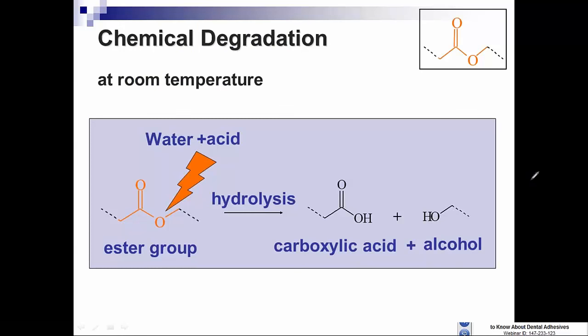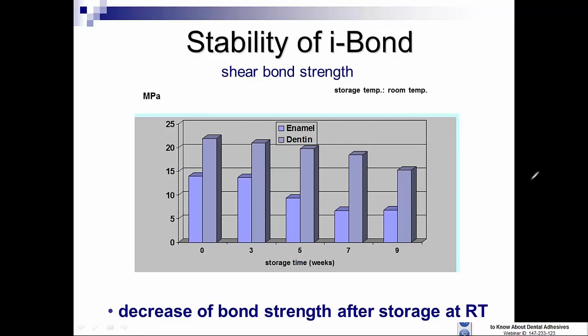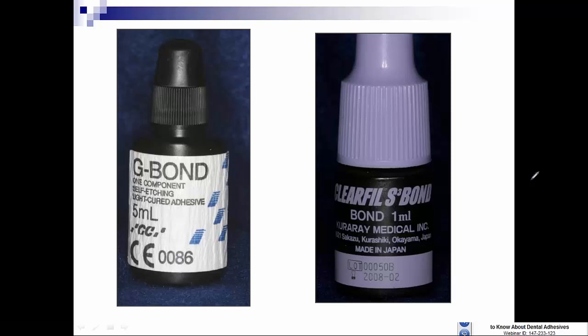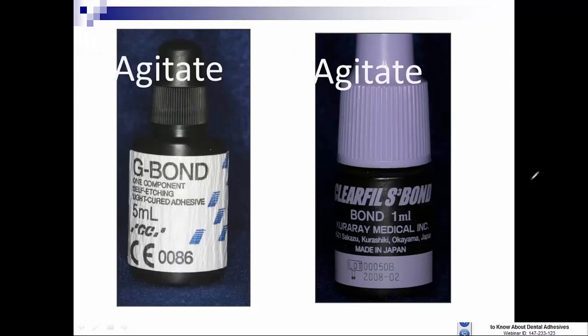But these materials, these phosphate ester groups, with room temperature storage can break down. And it's very important for self-etching systems that the instructions for storage in your offices be followed. Warm or even room temperature storage could create a situation where over time, and we can look at a product like iBond, which in a 9-week period of time had significantly reduced enamel and dentin bonding after room temperature storage, simply because of this hydrolysis of the active monomers in the tooth. So while these bottles look very simple, they're very complicated chemical mixtures, and careful attention to the treatment and storage requirements is important.